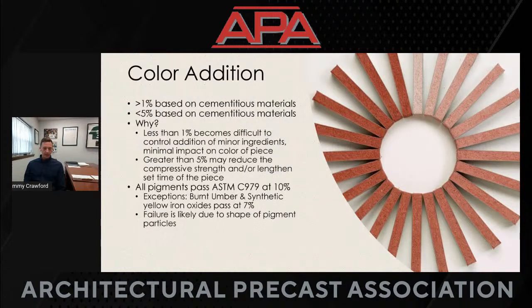Color addition. We generally recommend staying between a 1% and a 5% addition rate. Why is that? Less than 1%, it becomes difficult to control the addition of minor ingredients. Let's say you have 100 pounds of cement and you're doing a 0.5% addition rate. Your total addition is 1/2 of a pound. But of that 1/2 pound, let's say you're using a blend of 3 different colors, and one of those colors is a 10% minor ingredient. Now you need to weigh 0.05 pounds accurately and consistently to produce consistent concrete.